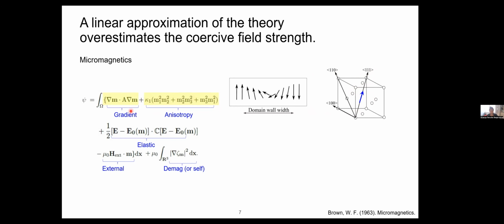And you have other energy terms like the gradient energy term, which captures the penalty when the magnetization is rotating from one direction to another. In the case of microstructure, it's the penalty introduced by a diffuse interface where the magnetization has a gradient. And then you have the elastic energy term. This is the energy term inside which your magnetostriction constants are buried. Essentially, when you have a material that's magnetized in a random orientation, and you apply an external field, you're reorienting the magnetization to align with your applied field. And this reorientation of the magnetization is also coupled with some stretching of your material. So there's a strain coupled with this magnetization rotation, and that strain is what is quantified by magnetostriction.